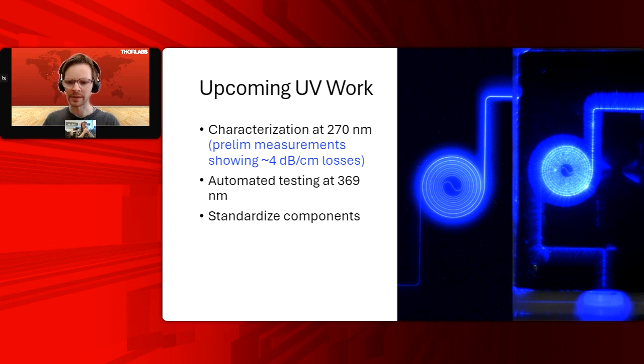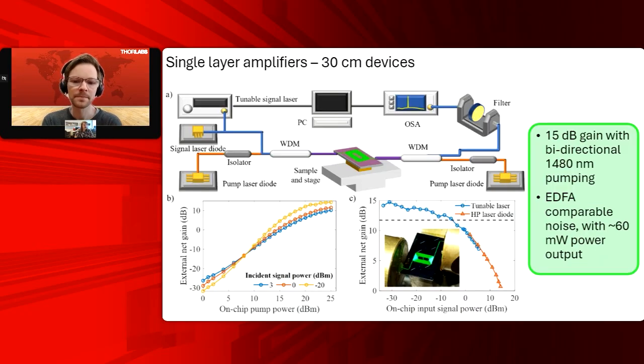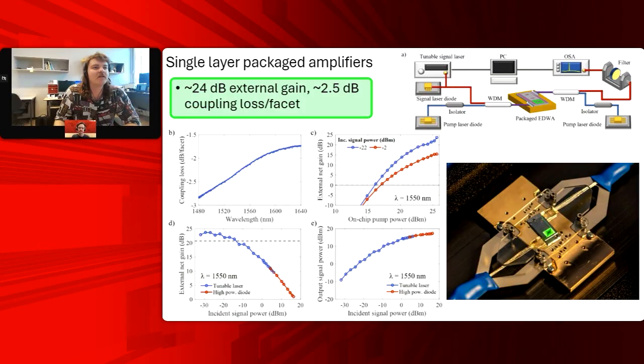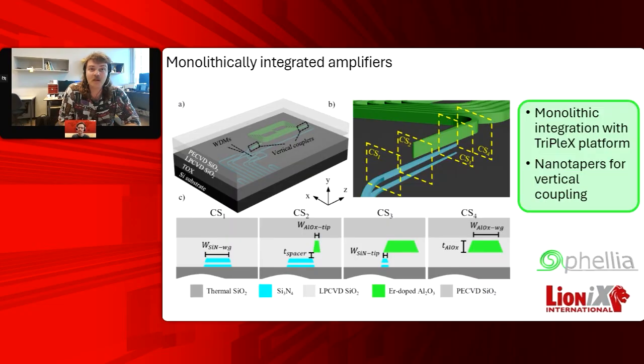Another question that came up, especially with the higher power amplifiers that you're using, is how much heat comes out of these devices, and what are the challenges with handling it, if any? We actually haven't seen any thermal challenges yet. It's maybe most prevalent on the thulium work I was showing at the very end, where they were doing pulsed operation. They did have some failure of the material. I don't want to speak too much for them because I didn't do these measurements, but all of their failure was in the silicon nitride, not the aluminum oxide. We know ruby and sapphire are among the most chemically robust and mechanically hard materials known to mankind, and so it's extremely thermally insensitive.